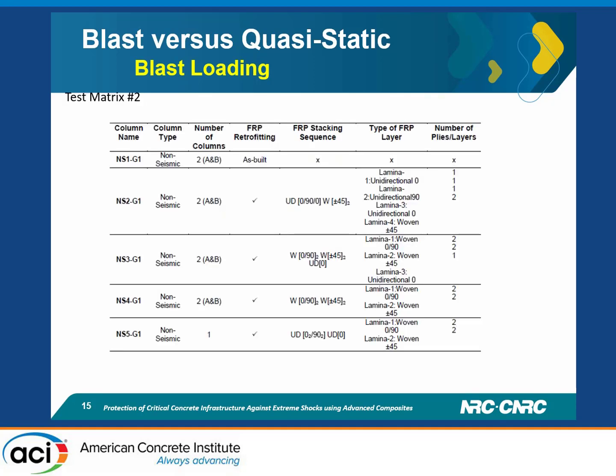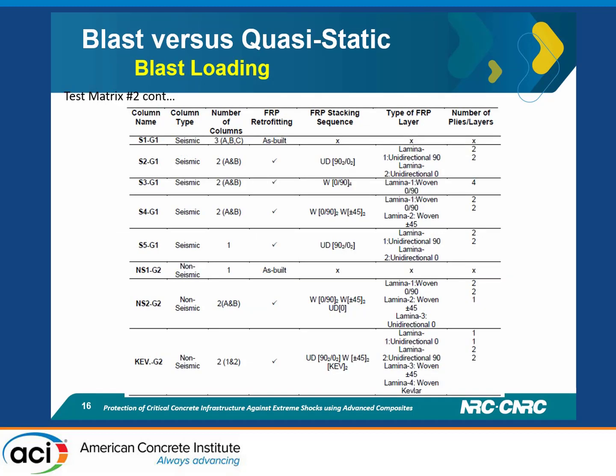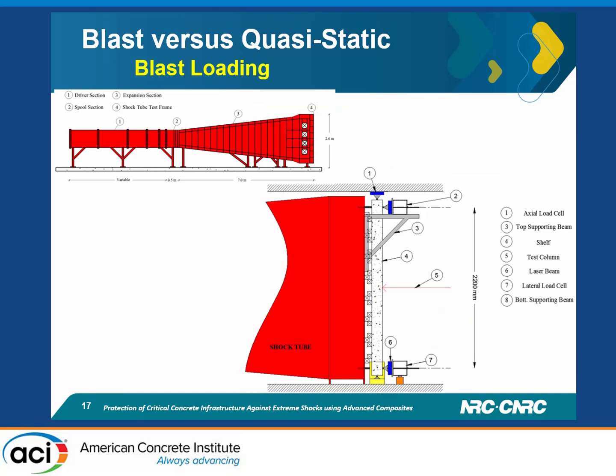The second matrix is to explore the effect of FRP of different orientations. So we have laminates formed from different layups and different orientations of the fibers. The FRP is CFRP with epoxy resin in this case. And here are details about what type of orientation and how many specimens for each test, and I will show you a sample of the results. We used the University of Ottawa shock tube.